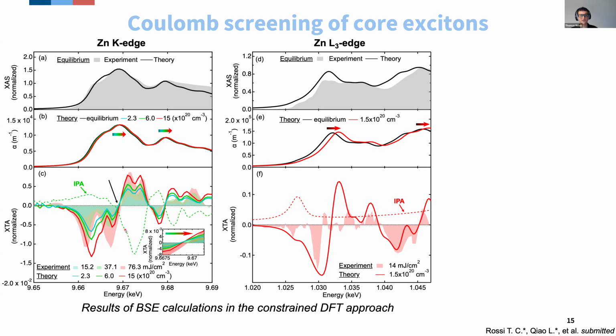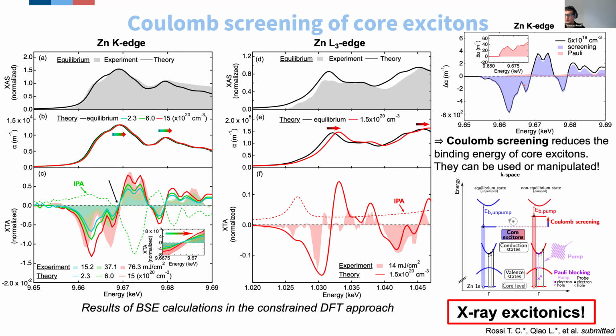And now remember that we can dig even further into what is the origin of this signal, by splitting the different contributions to the signal, so there is this Coulomb screening and the Pauli blocking. And what Lu found is that the dominant contribution to what you observe is a Coulomb screening contribution. So the origin of this pump probe signal is that the photoexcited carriers that you have generated with your pump pulse actually screen the core excitons and reduce their binding energy. That's what explains the blue shift of these excitons. And not only can we blue shift these excitons, but we can also blue shift them by different amounts, depending on the excitation density you use to excite the zinc oxide thin film.